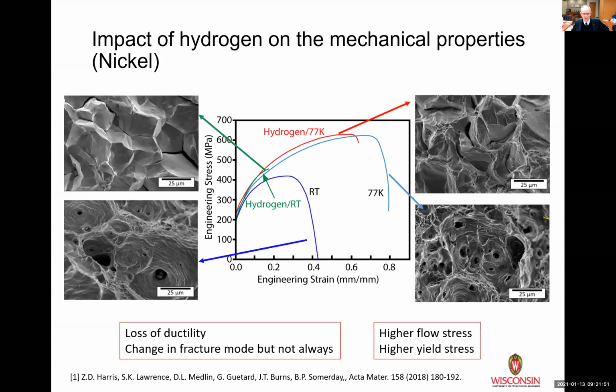And nickel is kind of nice because to accompany that reduction in the ductility, you also get a change in the fracture mode. So it makes it nice and easy to say that there is a big difference and there's been a different failure mode. So what you see here is that in the SEM images, in the absence of hydrogen, you get the ductile type fracture that we're all very familiar with. When hydrogen is present, you actually get intergranular failure. And you can see that in the upper images, you can see the grain boundaries quite nicely. So this is what happens when we put hydrogen into the system.